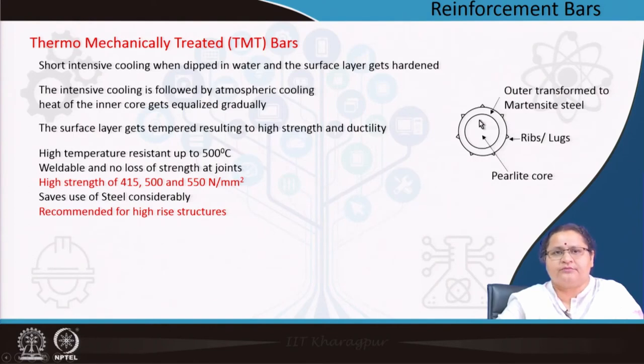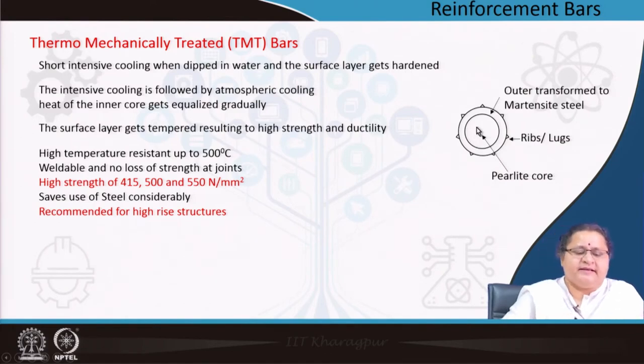Inside is still hot. It is still changing the crystallization pattern of this martensite steel, and this gradually cools in the atmosphere. Outer remains martensite, inner remains pearlite, exhibiting different kinds of properties. It gives higher strength and ductility, and also high temperature resistance up to 500 degree centigrade.